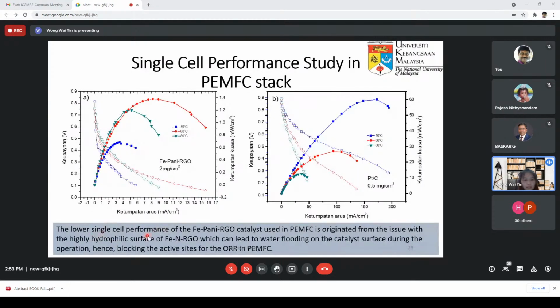So we speculate that the lower single cell performance of the Fe-Pani-RGO catalyst used in the PEMFC originates from the highly hydrophilic surface of the Fe-N-RGO. That can lead to water flooding, because we know the product of the electrochemical process is water. Since the surface of this catalyst is hydrophilic, water tends to adsorb on the surface. Once it adsorbs, it will block the active sites for the next batch of reaction.